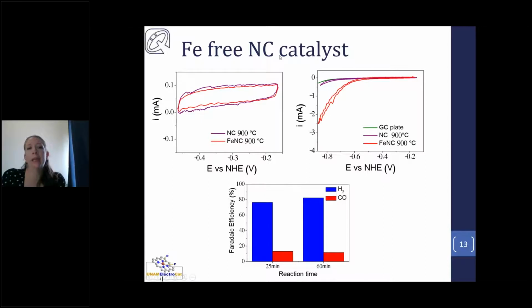we prepare an iron-free catalyst, and this is what I'm showing you here. We characterize the electrochemical surface area, and we see that it's basically the same for the iron-free catalyst. But when we look at the current during cyclic voltammetry, we see that when we have iron, the reduction current is considerably larger. In terms of selectivity, here we see the selectivity of the process on the iron-free catalyst, and we see that although in the absence of iron, some CO2 is being reduced to CO, the main product is hydrogen.